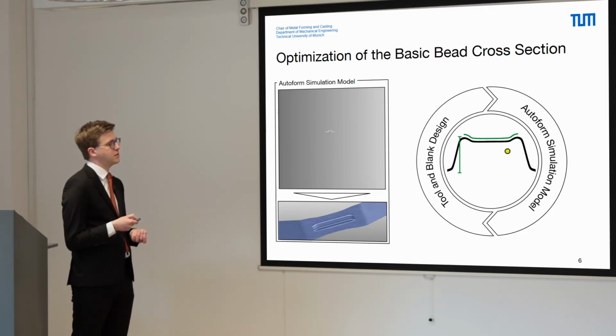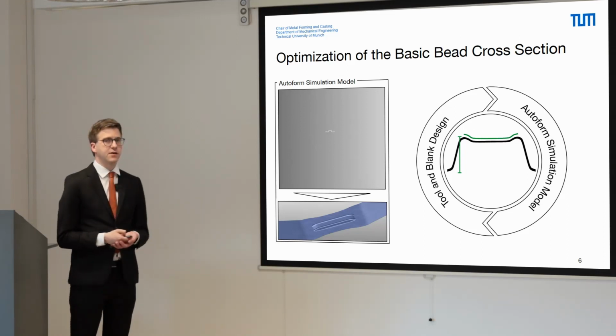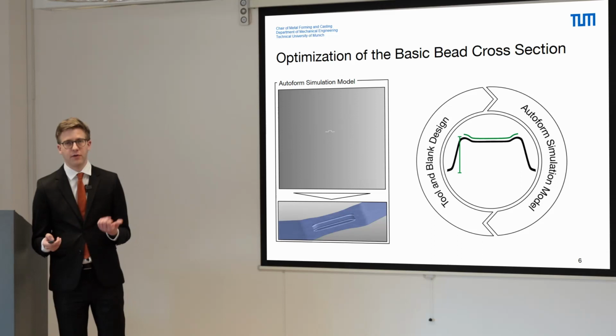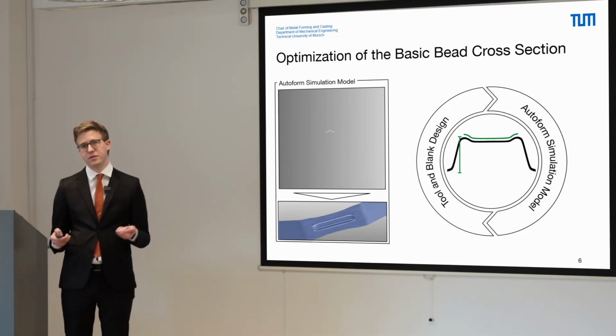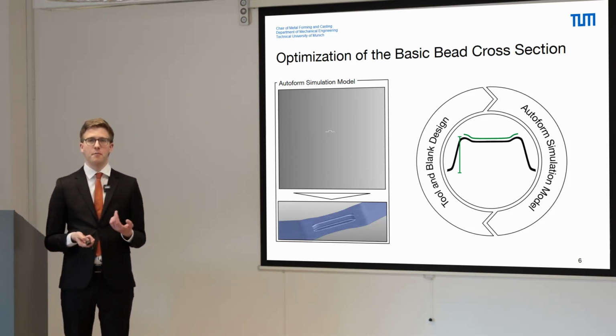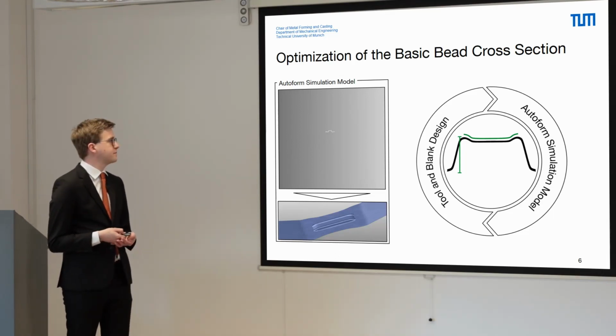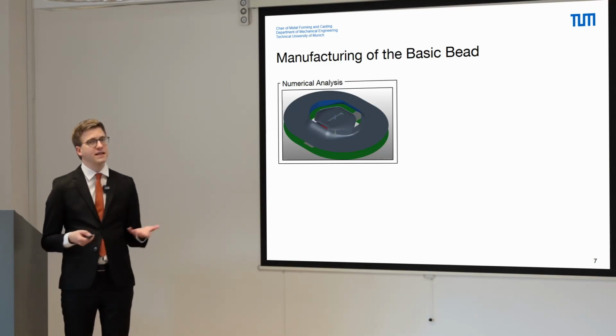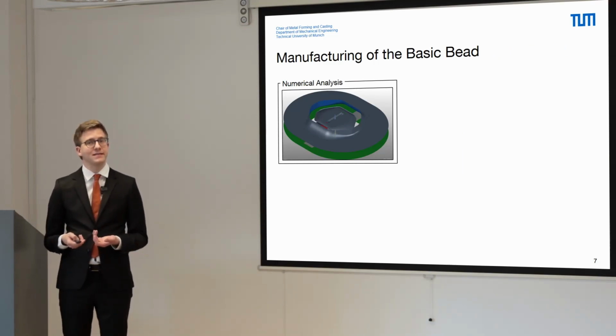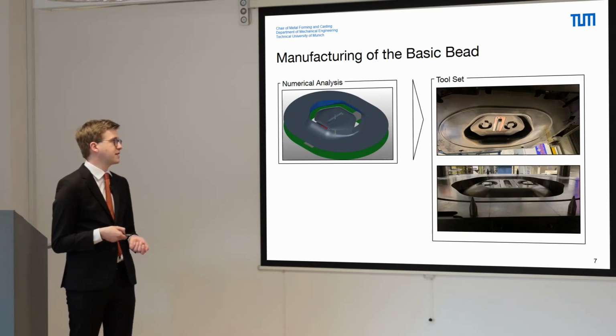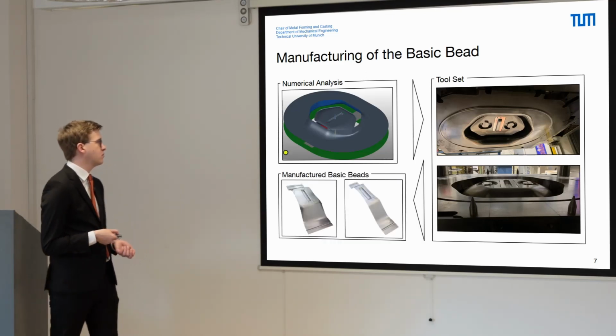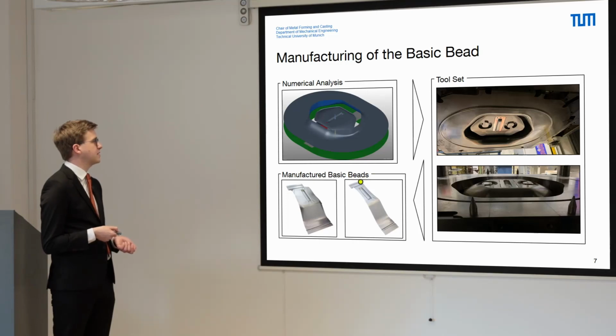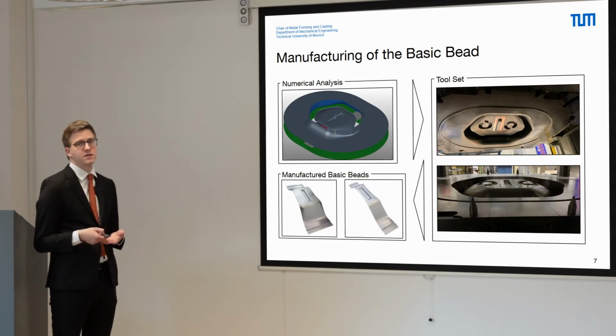fiber reinforcement will be placed, and a larger bonding surface, a larger adhesion surface will generate both a higher bond strength and a higher reinforcement effect due to the larger amount of possible UD-CFRP. So, based on the results of the numerical analysis, the toolset was manufactured and we were able to generate the basic bead geometry without the appearance of tearing for the DX56 steel.